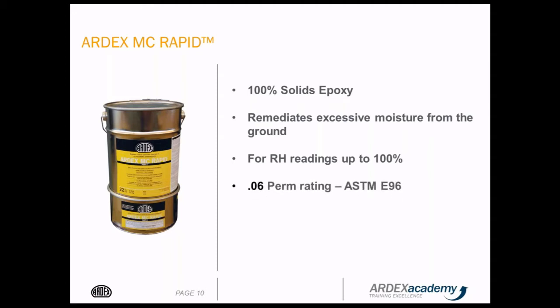MC Rapid has a very low permeability. The standard for testing permeability is ASTM E96. Upon conducting this test on MC Rapid by independent third parties, we established a perm rating of 0.06.